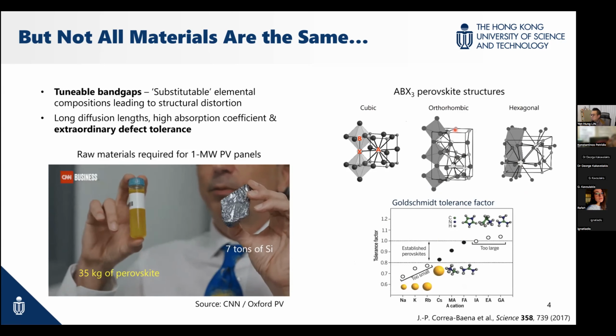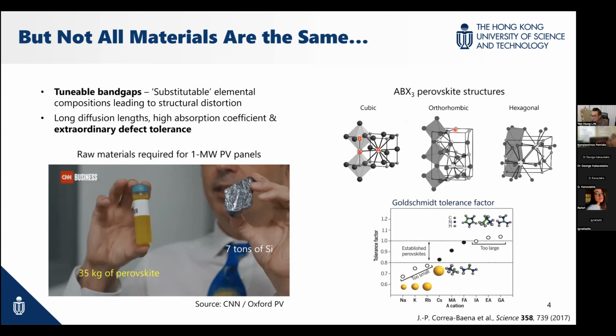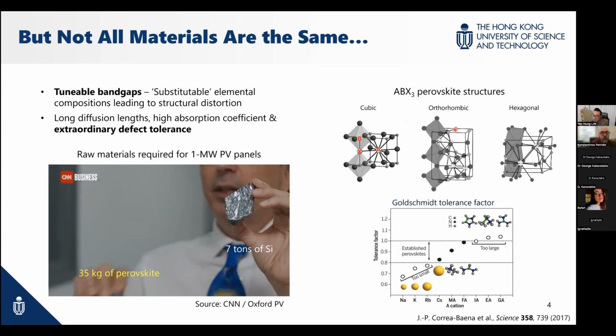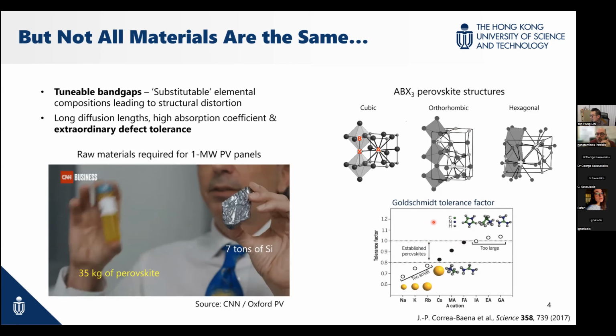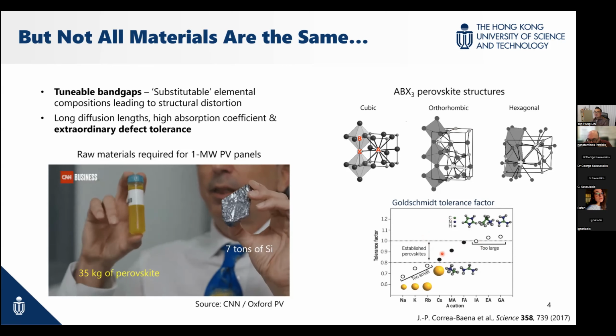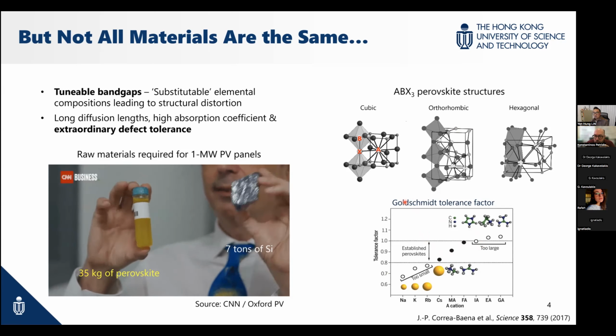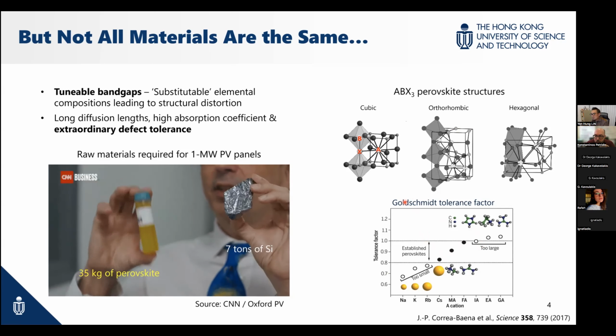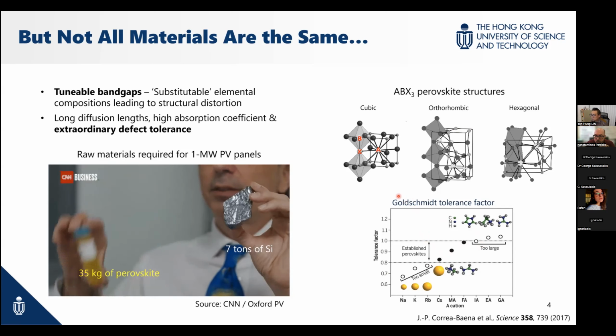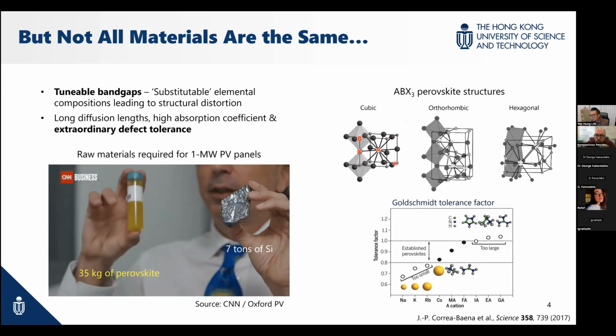Perovskite has an ABX3 structure, with a monovalent cation on the A site, a divalent cation on the B site, and the X site normally a halide. There are a couple of candidates we can use, not just methylammonium but also formamidinium. As long as you follow the Goldschmidt tolerance factor, we are able to form a perovskite. But with different sizes of atoms or molecules, we do not necessarily form cubic structures and may have strong strain, which might not be ideal.